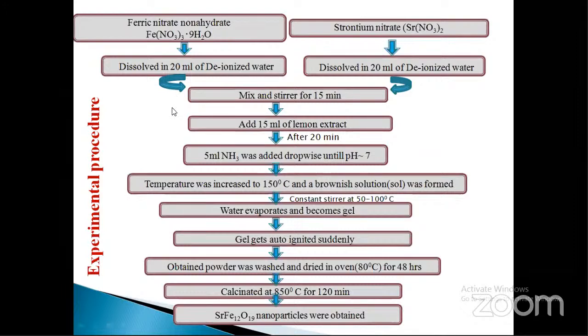And this is the experimental procedure. My main precursors are ferric nitrate nonahydrate and strontium nitrate. Both were taken in stoichiometric ratio of 12:2 and separately dissolved in 20 ml of deionized water, and both mixtures were stirred for 15 minutes. And I have used green synthesis.